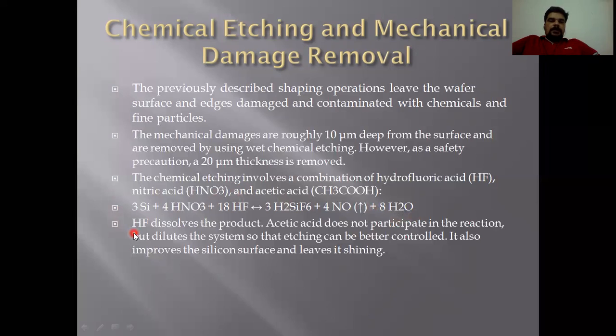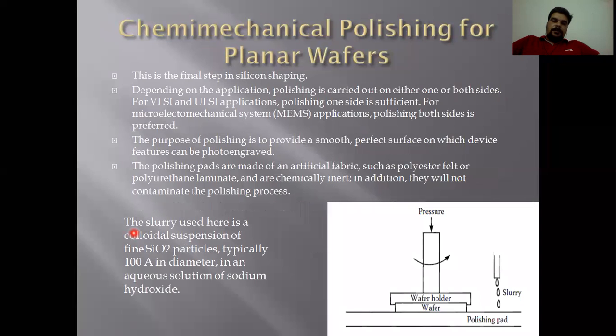So what is the role of the hydrofluoric acid? It basically dissolves the product. Acetic acid does nothing in the reaction, but only dilutes the system so that the etching can be better. It also improves the silicon surface and leaves it shiny. Now, this is the chemical polishing for planar wafers. This is basically the final step in silicon shaping.